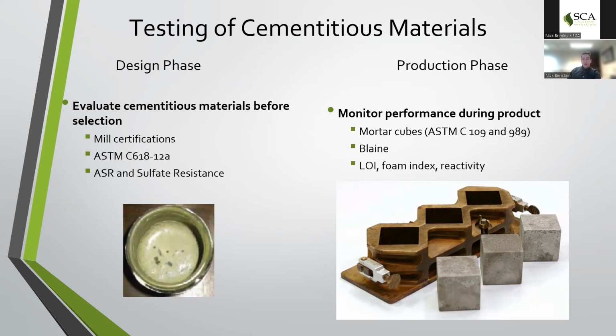Before and during the design phase, one of the most important portions of this is evaluating potential supply lines. We do this on both a quality control level and also on a procurement level, ensuring that you're going to have sufficient amounts of material to the best of your ability while going through a project can help. High performance concrete often has heavy pre-workup in terms of laboratory testing and assessment. So if you have to make changes to those material sources midway through the project, it often requires retesting of those materials to verify that performance will meet or exceed recent mix designs. So securing those sufficient supply lines and also testing that the quality will continue to remain is very important, whether that be through documentation such as mill certifications, specific testing such as 618, and then for your aggregates, evaluating for ASR and sulfate resistance, and any sort of mitigation that might be required for actual placement conditions.